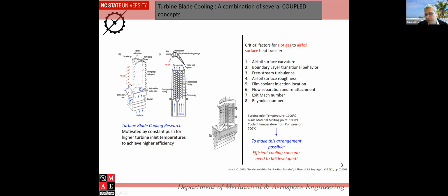To make this efficient, and of course, remember, I also told you at the beginning, I have only 10% of the air that I get from the compressor. That means I have a limited amount of air at a particular pressure that needs to be used to cool the blade, right? So now the point is, I have a limited amount of cooling air. I have to get this temperature below 1000 degrees centigrade so that it can sustain life.